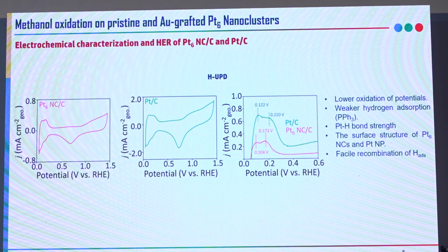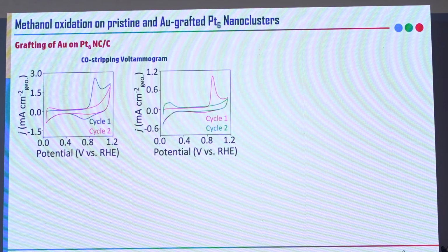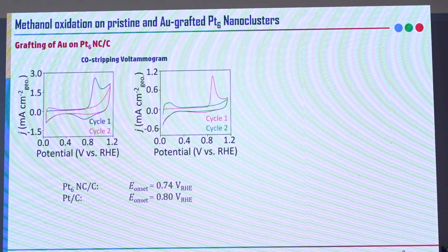We characterized them using a basic electrocatalysis parameter, that is the hydrogen UPD. In the hydrogen UPD, you can see there is a negative shift in the hydrogen desorption peaks compared to the commercial Pt/C. That means the hydrogen bonding with the platinum 6 is less stable, or the energy is very low compared to the commercial Pt/C. While doing the CO stripping voltammetry, we were able to get a lower potential for the CO stripping. That is why we are using the adsorbed CO as a reducing agent for the decoration of Au3+ on the surface of these platinum 6 nanoclusters as Au0.